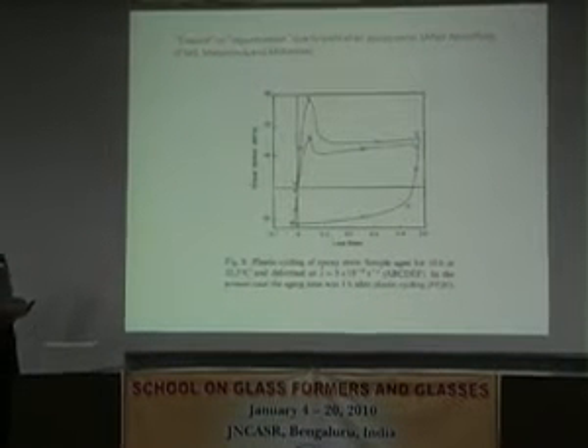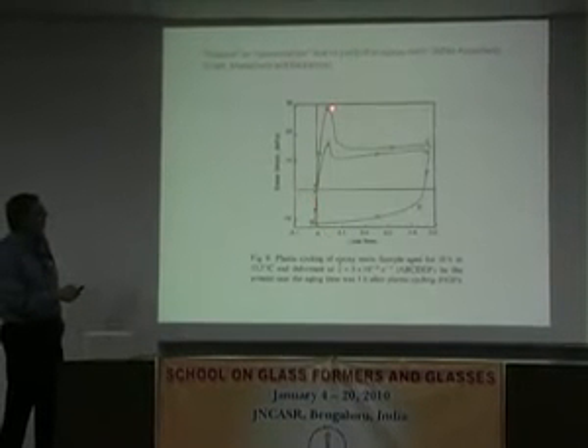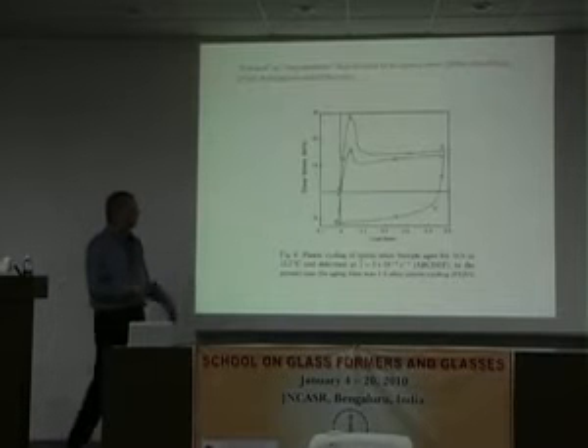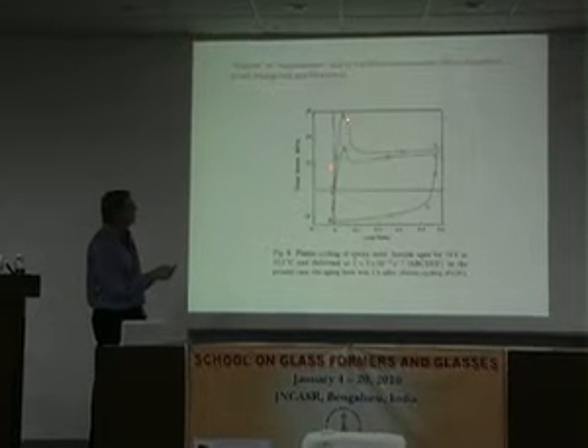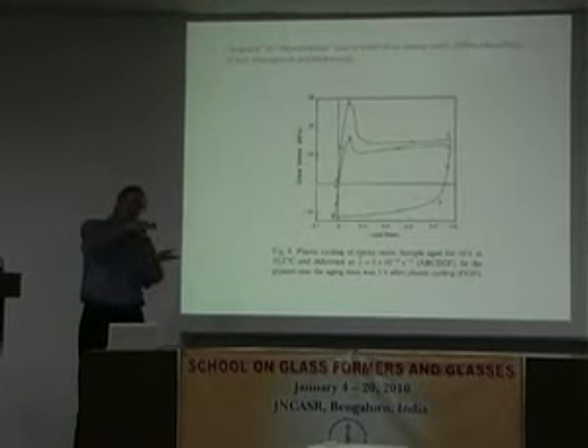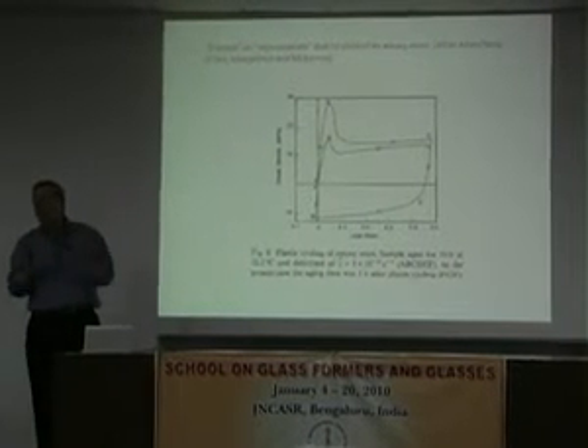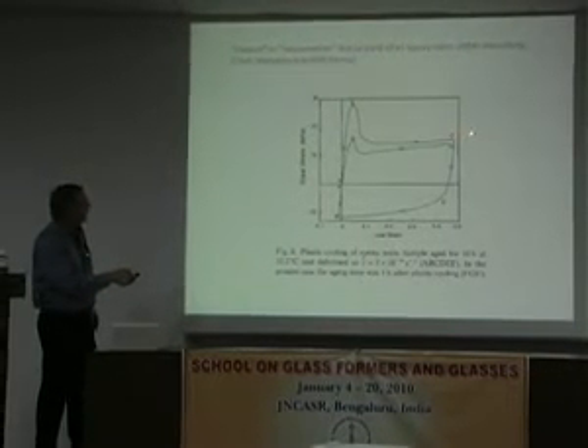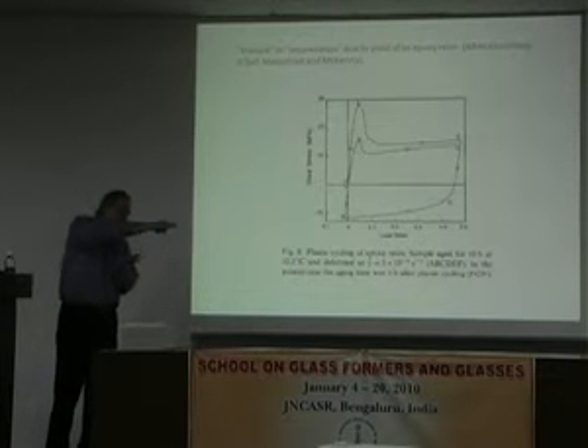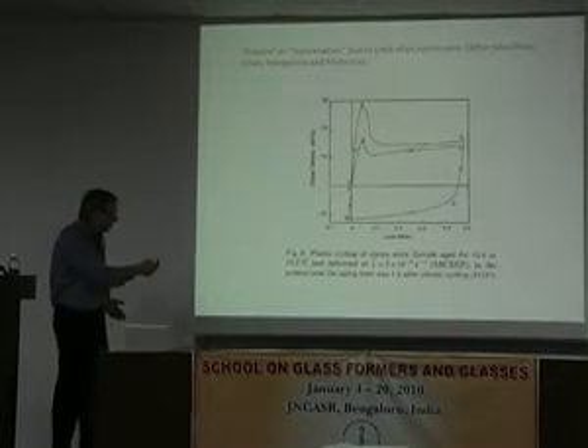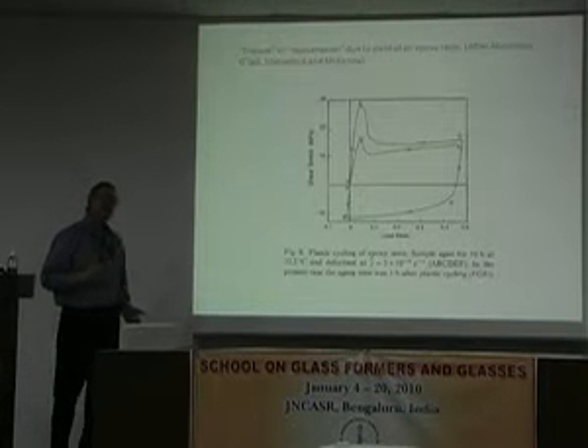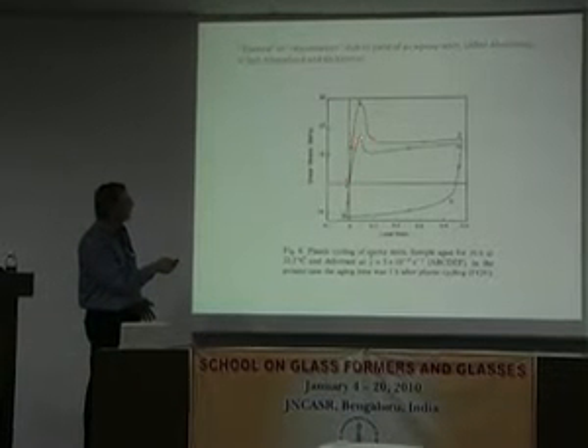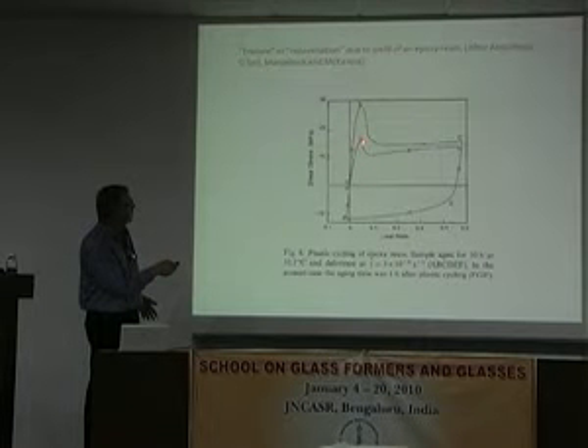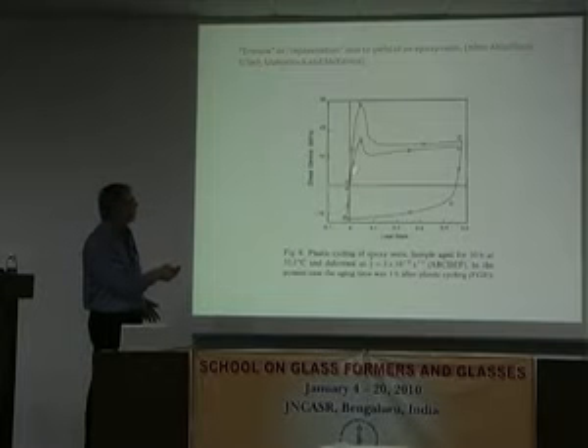Okay, so this is what yield looks like. What we did then was we decided to do a set of experiments where we're going to watch that yield stress build up as a function of aging time after a thermal quench, and then we're going to compare it with an experiment where we go, in this case, to 50%. Now, these are shearing experiments. These are really elegant experiments that Christian Gazelle designed. And we can unload it, so you shear it and unload it back just enough so that when you get back to zero, you're at zero stress. And then we're going to run it up and take a look at this behavior. As a function of time after we did this first cycle, we just want to watch and see what happens to the yield stress.